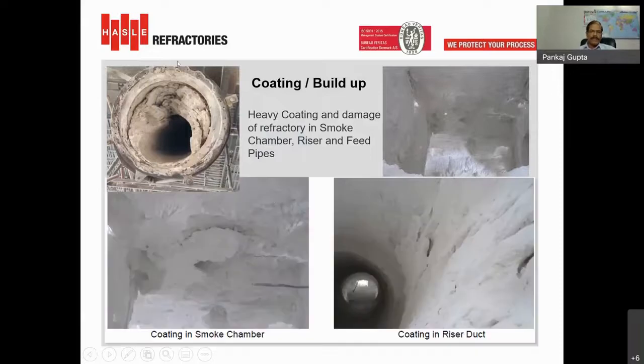Here I'm sharing some pictures from the plant. You can see here a feed pipe with a lot of coating, roughly more than 60% of the area packed with coating. And you can also see a picture of the smoke chamber and riser duct. You can see a lot of coating in the system. And actually this hampers the flow of the raw material in the process.